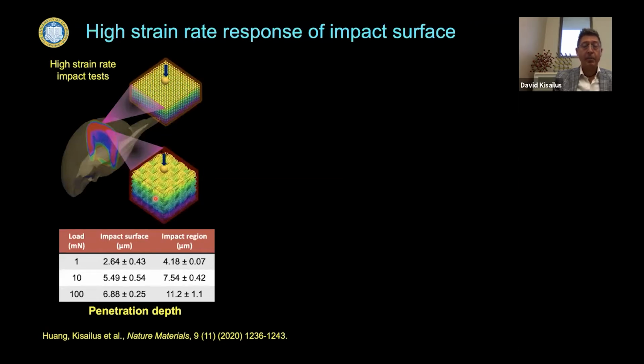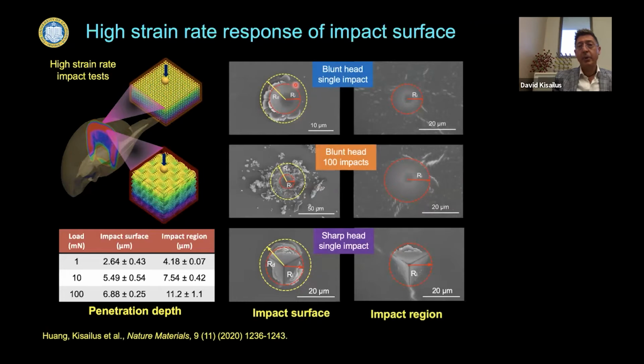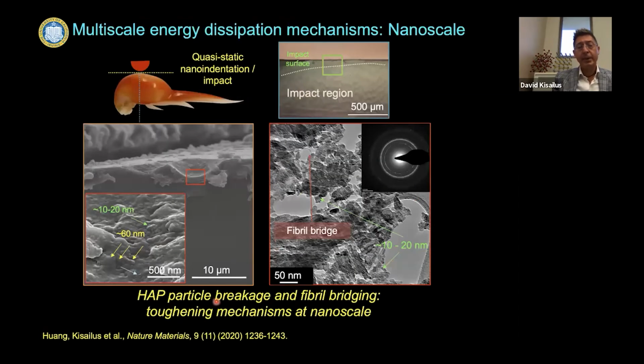So the impact surface particles are removed. And you can actually see from a single impact the particle pileup that's occurring. Whereas on the right side, when we remove those particles, you can actually see these cracks developing. And this is after 100 impacts, and then also with a sharp head upon impact. And so after those impacts, we can actually see something happening. Those 60 nanometer secondary particles do exist, but we also see some remnants of smaller particles that have fractured off from those 60 nanometer particles. So there's some particle breakage here. We also see some fibril bridging, that's the organic phase, that may provide toughening at the nanoscale.